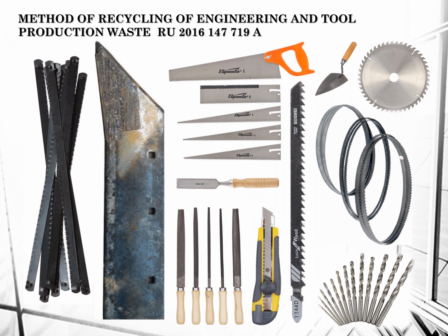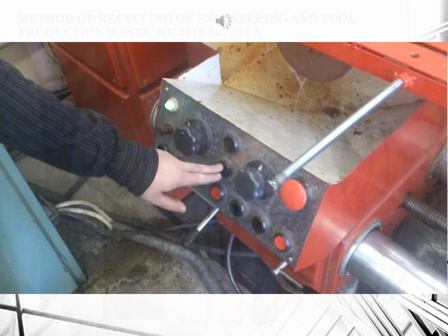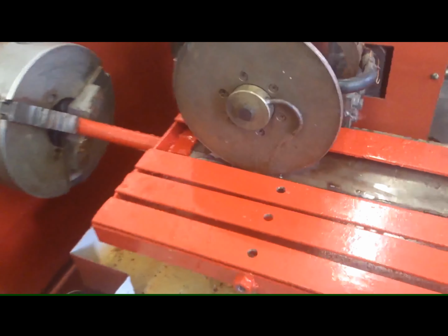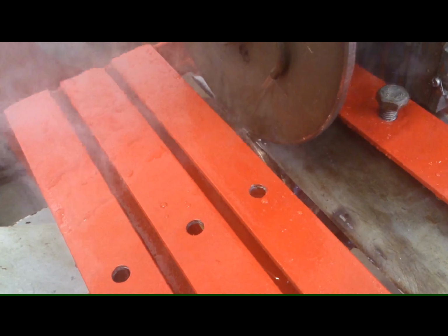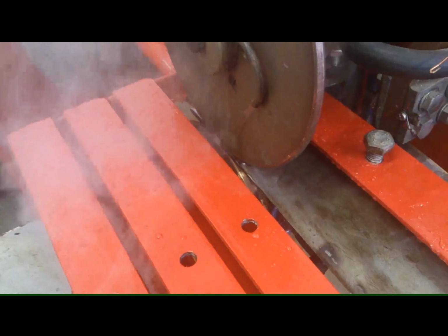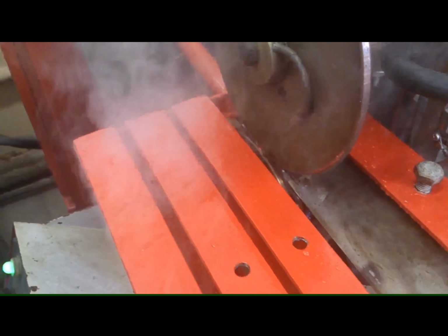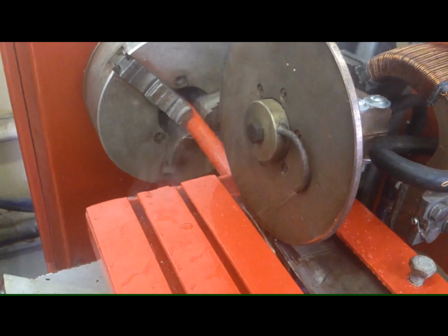With this technology, a wear-resistant coating was obtained on the zone, the toe, of the plowshare exposed to the greatest abrasive wear by electrocontact welding of unusable hacksaw blades made of steel grade 11R3M3F2. For the realization of this procedure, it was proposed to use the wastes of machine building, or other branches of industry, in the form of strips or wires made of structural, carbon tool, alloyed tool, or high-speed steel, manual, machine, strip, and jigsaw blades, files, broach files, drill bits, and their debris, as well as the cut and chipped ends and flash formed in the tool-making production.